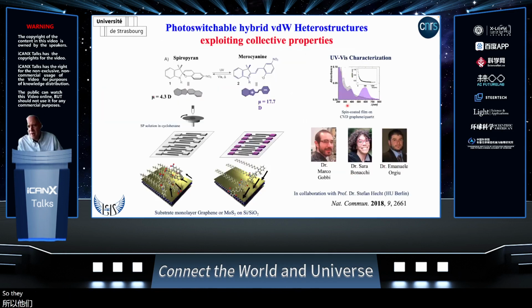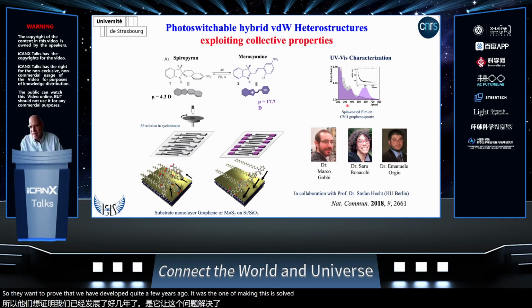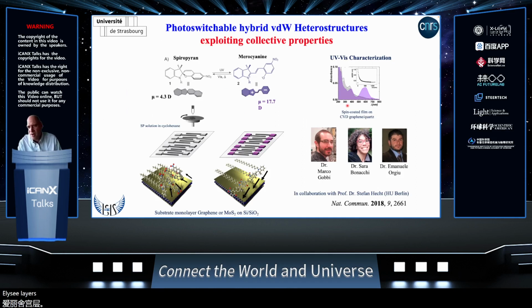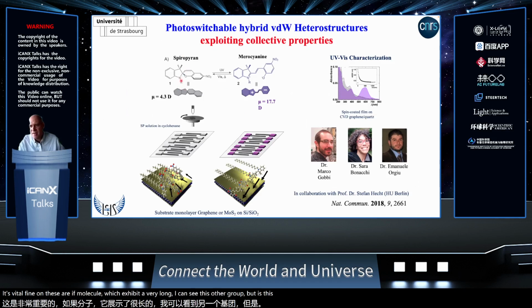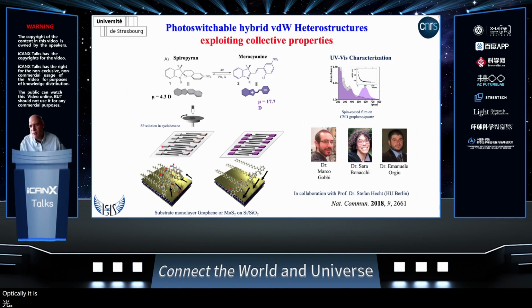So the one approach that we developed quite a few years ago was making physisorbed monolayers of spiropyran. These are molecules that exhibit a very long alkyl chain. This R group is a C18 chain. The C18 chain is this line here that templates the formation of this lamella structure, and therefore we position the optically responsive group in a well-defined position in space with atomic precision.